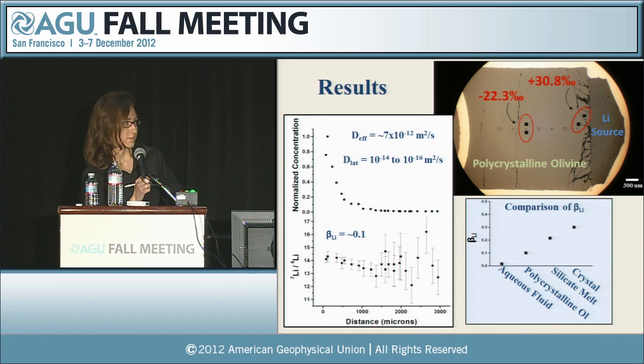Most of the experiments have been giving us beta values of about 0.1 so far. So this graph here just compares the beta values that have been found for lithium so far. Again, we have aqueous fluid, silicate melt, crystal, and polycrystalline olivine sort of sits in between aqueous fluid and silicate melt.